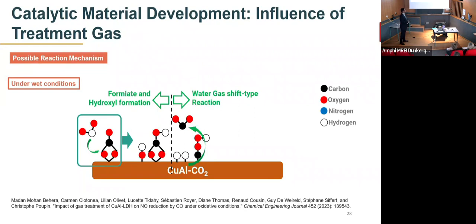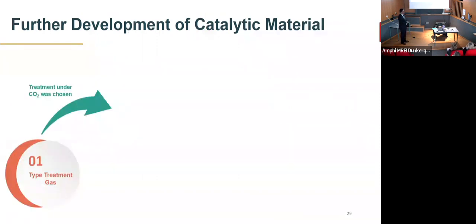And at the same time, we have the water gas shift-like reaction that we already saw in the previous slide, where we form this species that releases the carbon monoxide. We have the formation of the atomic hydrogen on the catalytic surface. We have its reaction with the nitrogen monoxide to form the hydroxyl group and the atomic nitrogen. And the atomic nitrogen interacts with another atomic nitrogen to form the dinitrogen or N2. So we see that the CO2 treatment of our sample gives us a good activity, especially under the dry reaction conditions. So we choose CO2 treatment as the treatment process for our mixed oxide samples.